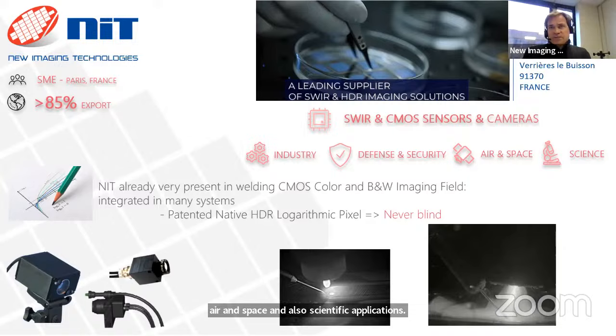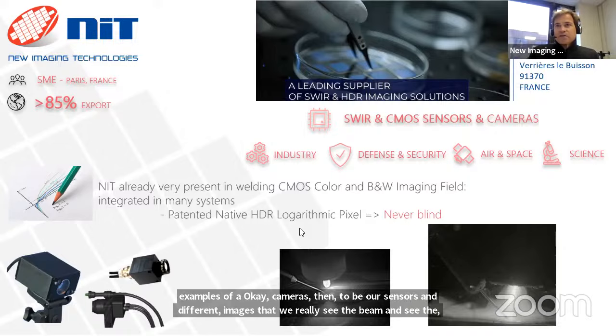We are already very present in the welding industry for our black and white and color CMOS sensors. We have customers that integrate between 300 and 500 cameras per year using our sensors. These sensors have something very specific, which is that they have a native HDR logarithmic pixel, which is inside each pixel of our sensors. So we basically are never blind. So here you can see examples of cameras that integrate our sensors and different images where you can really see the beam and see what you're looking at. So that's the interest of having this very high dynamic range pixel.